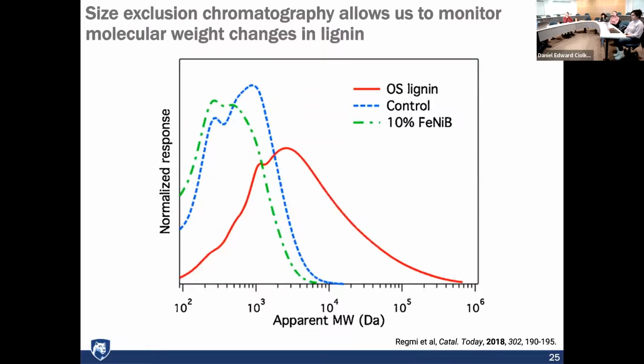So one way to track changes in lignin is by doing what's called size exclusion chromatography, which just gives us a molecular weight distribution. Here on this horizontal axis is the apparent molecular weight of lignin, and this is a log scale. So here we have 100, 1,000, 10,000, 100,000, et cetera. When you inject lignin into this instrument, you see that in fact, it's a heteropolymer whose structure is unknown and whose molecular weight is distributed. There's some small number of molecules that have a molecular weight of about 100, and some small number of molecules that have a molecular weight of nearly 1,000,000. And most of the molecules have a molecular weight of, say, 3,000, something like this.